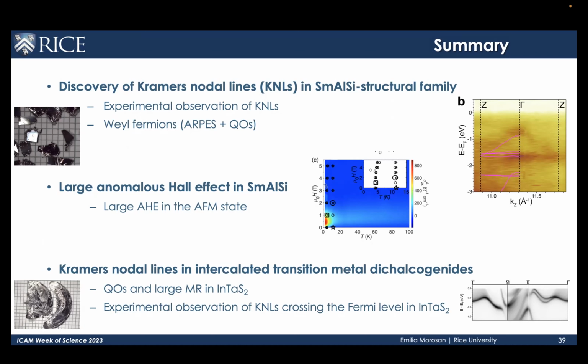Could you do core level spectroscopy? Probably. We haven't done it yet. Actually, I think ARPES resolves the samarium surface bands. This is something that came out very recently from Ming's group. They do see a small amount of 2+ from ARPES, but it's primarily 3+. So, yeah, there's a whole series of these rare earths that are 3+ in aluminum silicon. Neodymium is probably one of the better studied ones on this.